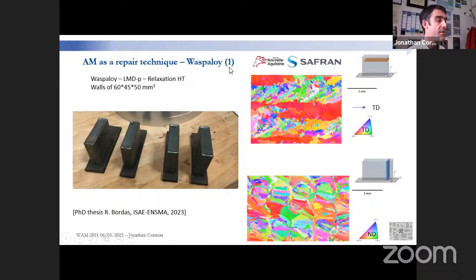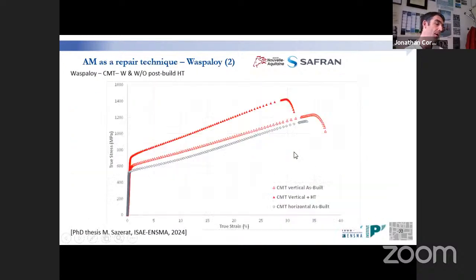Today, I will only show results on Waspaloy, which is a gamma prime strengthened alloy with nearly 25% gamma prime. We have been able to do the EBSD maps, so very typical microstructures for this kind of process. And the first thing we are studying is the role of heat treatment, since we are repairing components: what kind of heat treatment we can apply without degrading the properties of the substrate we want to repair, but improving the properties. And that's a tricky issue.